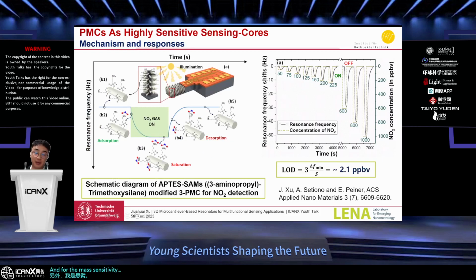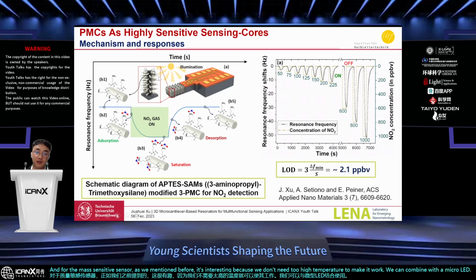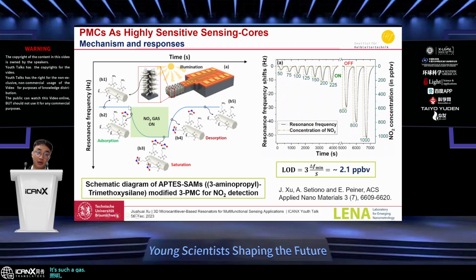for the mass sensitive sensor, as we mentioned before, it's interesting because we don't need too high temperature to make it work. We can combine it with a micro LED. So when the sensor is under illumination of a certain wavelength, a certain gas, like here NO2, can be adsorbed. And then when we change the light condition, the gas can desorb from the sensor, so you could have a clear signal of how the sensor responds to different concentrations of the gas, and it could reach a limit of detection of 2.1 ppb, which means parts per billion by volume. So it's very, very sensitive.